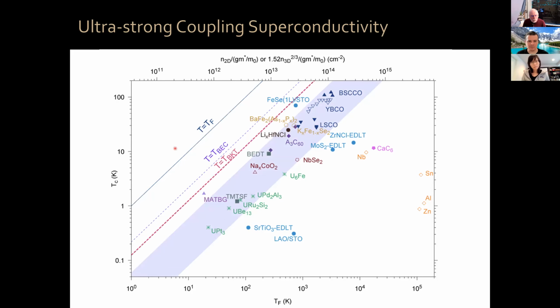This is the BKT, the upper bound for the BCS-BEC crossover for TBKT, okay, in 2 dimensions. Magic angle twisted bilayer graphene, okay? Depending on whether you look at TBKT or 50% normal state resistance, those data points are here. For the trilayer case, those data points are here, okay?